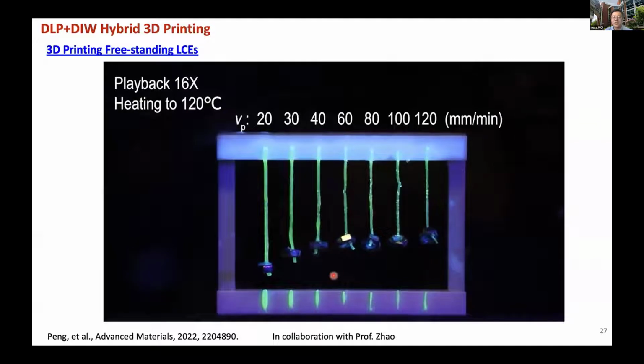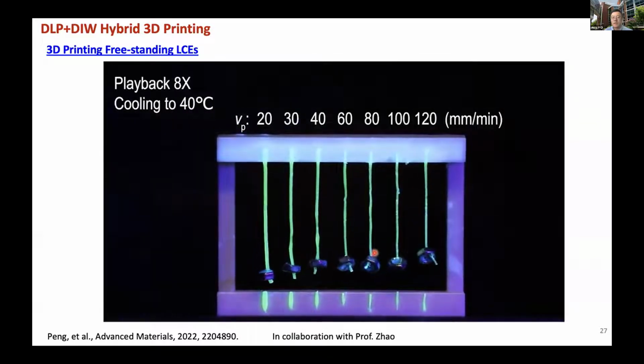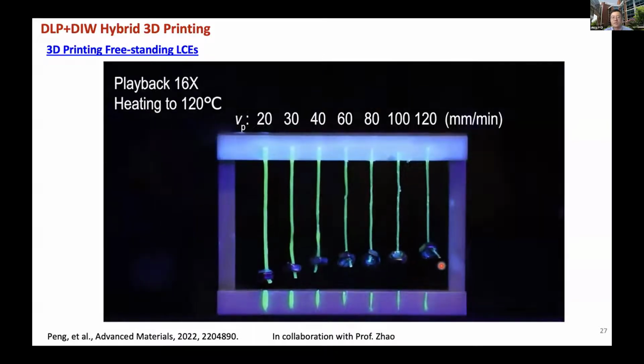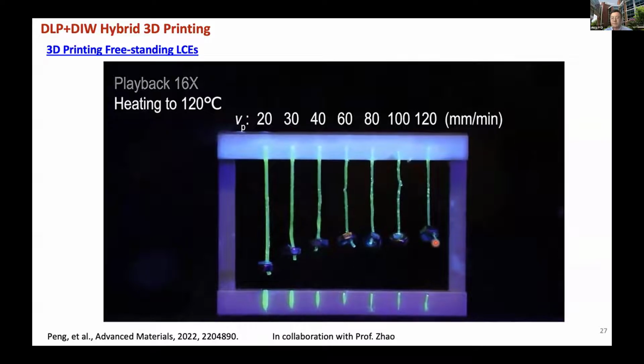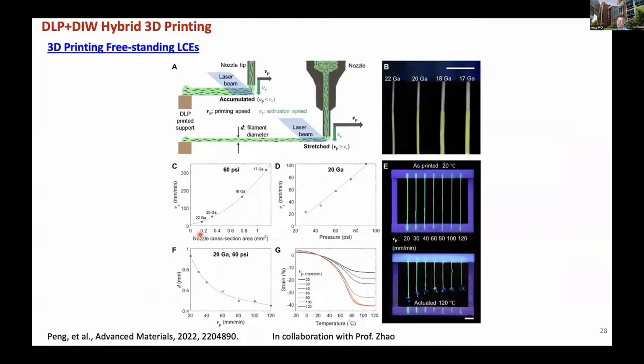The interesting thing is that at roughly 80 to 100 millimeter per minute and above, the alignment starts to saturate. But certainly, the higher printing speed gives you some alignment. We did quite a thorough study on this. The idea is that we want to print very fast, because as we extrude the liquid, the mesogens are aligned, but probably not to a significant amount. So we move the nozzle really fast, the printed filament is stretched, and after stretching you further align the mesogens, and then you shine the light and cure it. So it's really a combination of extrusion, alignment, and the printing speed mismatch causing alignment.